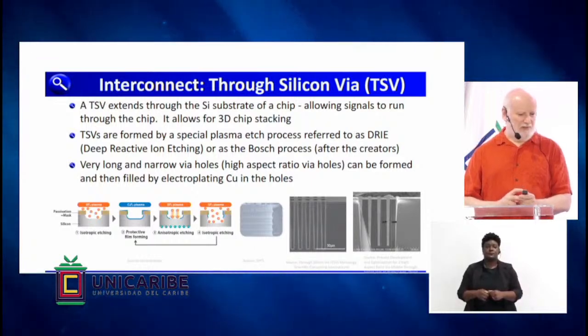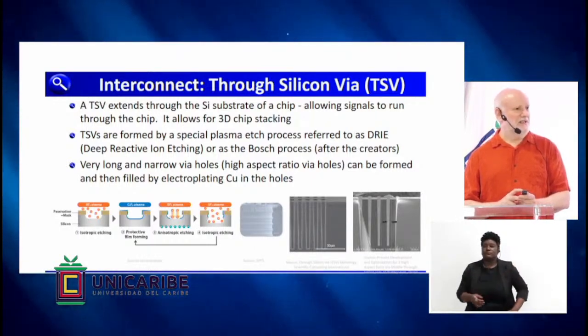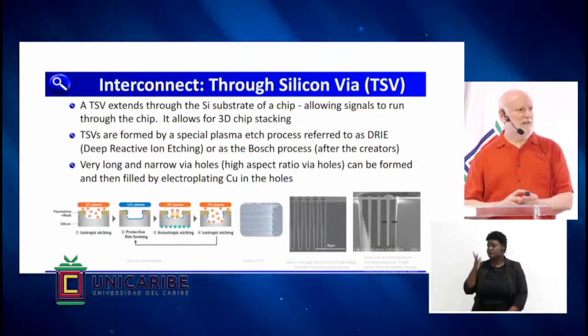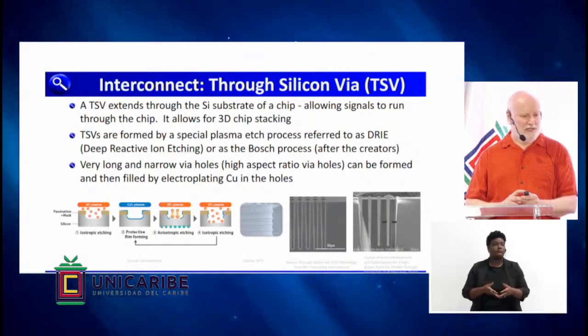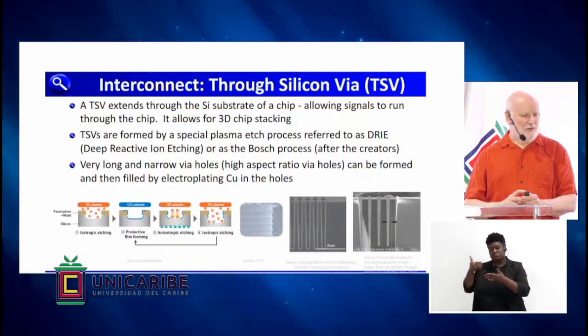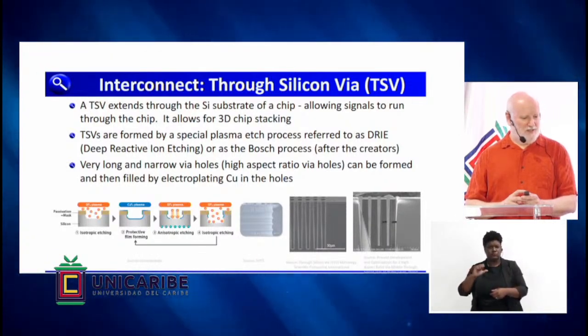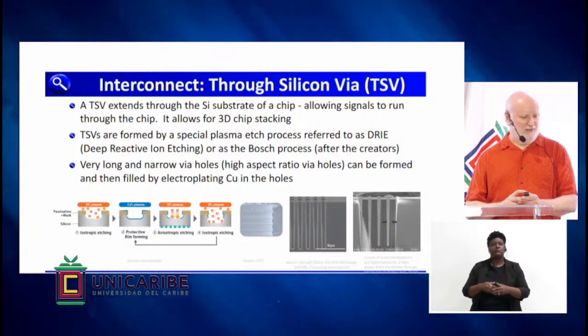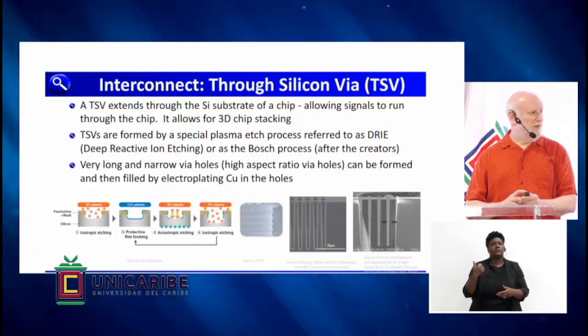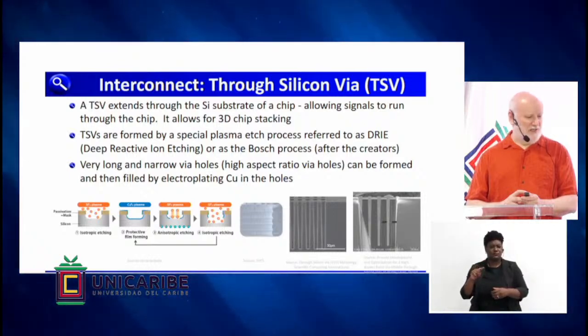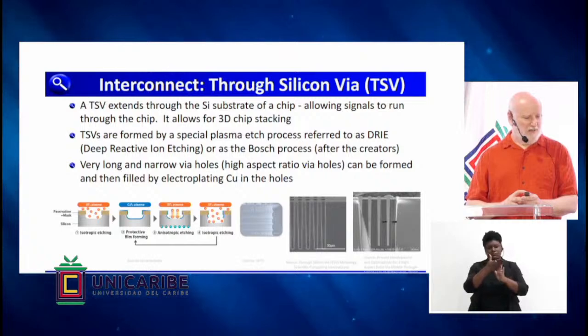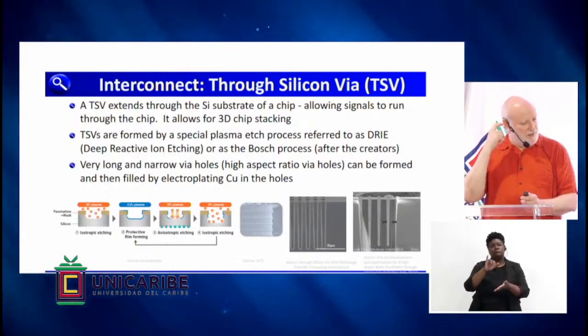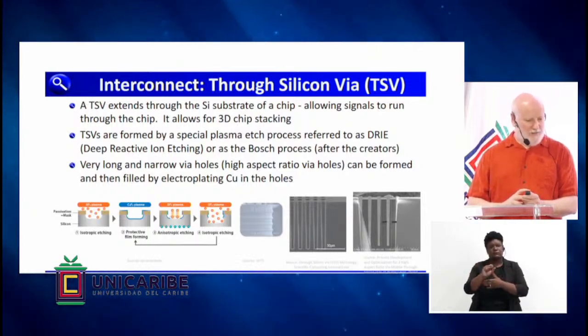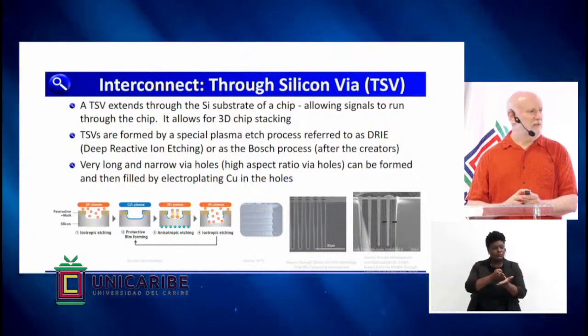So let me talk a little bit about through silicon vias. As I said before, these are vias that extend all the way through the silicon chip. And so you can route signals from the top to the bottom, or front to back, of the chip. And they're formed by this specialized plasma process we call deep reactive ion etching. The process is pretty interesting in that you have alternation of an etching step and then a deposition of a polymer on the sidewall, and then you etch again, and you continue this down through, and so you get this scalloped edge of the via if you look closely at that picture in the center at the bottom. But these vias can have very high aspect ratios. By aspect ratio, I mean, how deep is it compared to the diameter? And so that's very advantageous because you can have very dense pitch then.